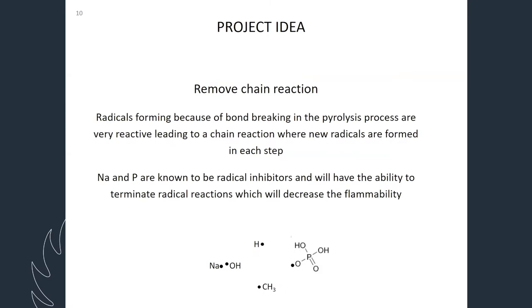And finally, we can remove the chain reaction, because radicals are species with unpaired electrons that form when bonds break in the pyrolysis process. And those single electrons make those radicals very reactive. So that starts the chain reaction, where new radicals are formed and the fire progresses. But sodium and phosphorus are known to be radical inhibitors. So they will have the ability to terminate those radical reactions, which will decrease the flammability and slow the progress of the fire.